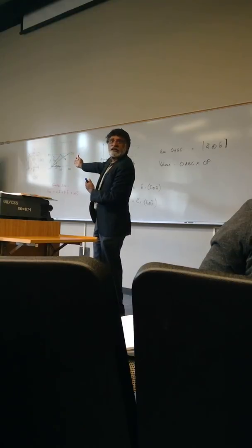And since this line is common to all of these planes, the reciprocal lattice vector, for each of these planes, will be normal to the set of planes. That's how we define the reciprocal lattice. So the G vector, that is G_HKL, is going to be H times A star plus K times B star plus L times C star.